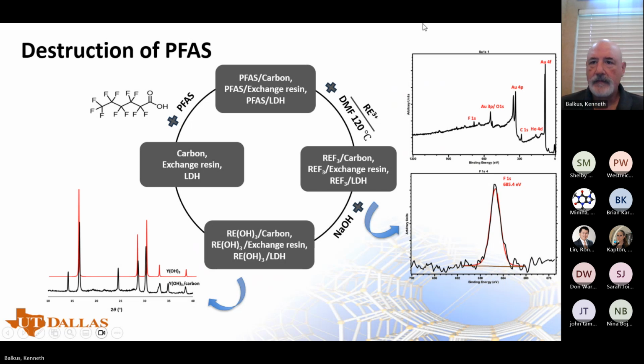and you can complete the whole cycle again. And so if you're trying to envision how this would work, you'd probably have to have a couple of beds where you could adsorb the PFAS, convert it to the metal fluoride, and by the way, the product here that you're ultimately going to make is sodium fluoride. If you take sodium hydroxide and metal fluoride, you make sodium fluoride, which can be used elsewhere. You could even fluoridate water with sodium fluoride. So that's the system that we ultimately came up with.